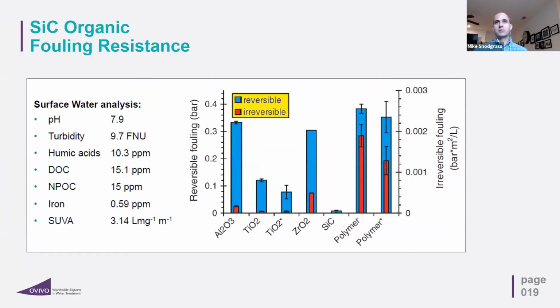This is a study done by a university in Germany looking at surface water, comparing all different types of membrane chemistries, both ceramic and polymeric. And they looked closely at both reversible and irreversible fouling. As you can see with SiC, it had the lowest amount of reversible and irreversible fouling. That's simply due to the hydrophilic properties of the material itself and its ability to repel a lot of organic material, as opposed to absorbing it into the pore structures and making it difficult to clean.